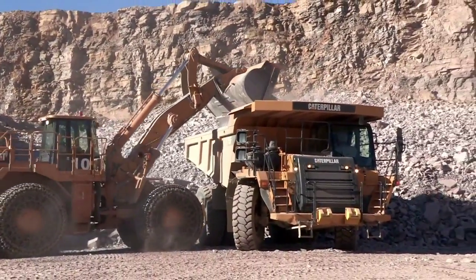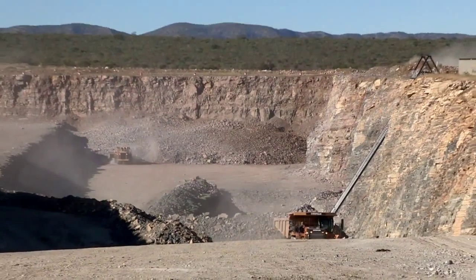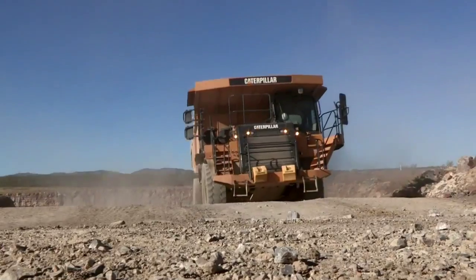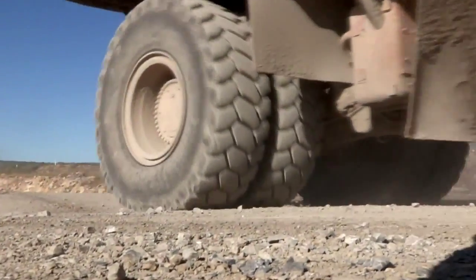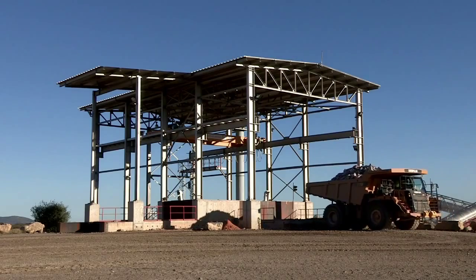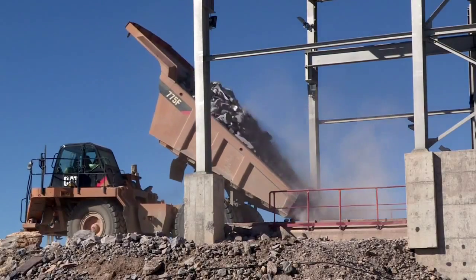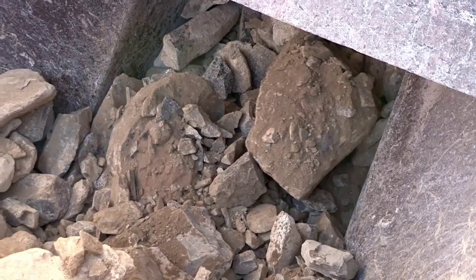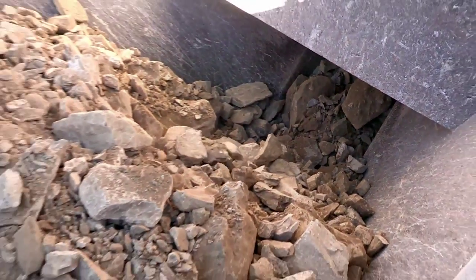The limestone, shale and marl rubble is loaded onto huge trucks with a loading capacity of 60 tons each. These raw ingredients are transported in specified ratios to the crusher, where they are ground to the consistency of rough gravel. The crusher can handle 600 tons of raw materials per hour.